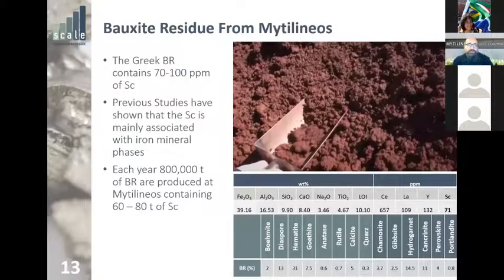So in our case, the bauxite residue contains 70 to 100, and sometimes even more, up to 130, ppm of scandium. I have to explain this. It is largely dependent on the initial mix of bauxite ore used in the plant. 3 or 4 years ago, we had much more Greek bauxite in our feed. In the last years, we have a bit more tropical bauxite in our mix, and therefore the amount of scandium has dropped. The scandium is located mainly in the Greek bauxite that we're using.